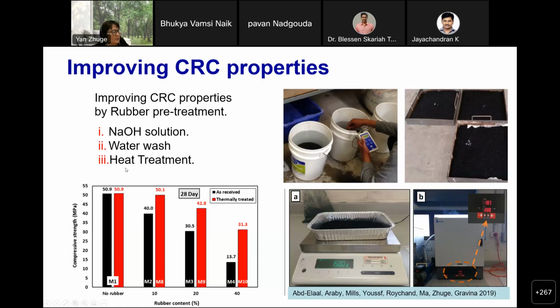Another method we tried was heat treatment. We call it thermal treated crumb rubber concrete. We just used a common furnace, you see the oven here, at a constant temperature of 200 degrees, not very high. Then we tried several different heating times, varying from 1 hour, 1.5 hours, up to about 2 hours. In the end, we found that 1.5 hours provided the best results.